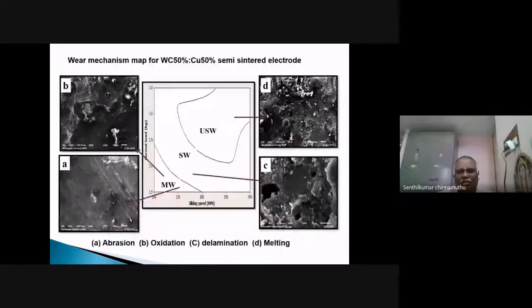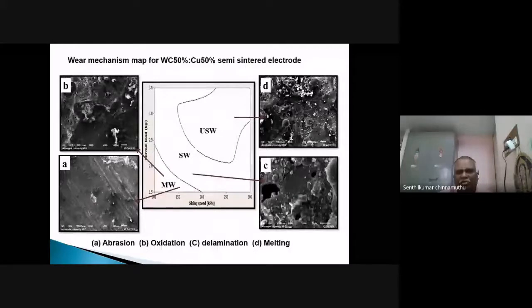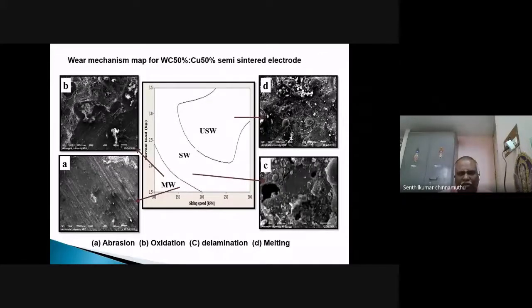Wear mechanism for tungsten carbide 50% and copper 50% semi-sintered electrode. See, in the mild wear region, that is the sliding speed of 100 to 200 and the normal load of 1.5 to 2.4. In this region, called the mild wear region, abrasion and oxidation take place.